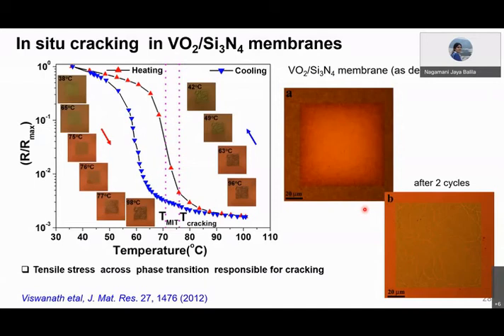Yeah, in this case, if you look very closely, the cracking happens only in the freestanding square membrane. The silicon nitride is coated on a silicon substrate. The outer region is thick, whereas the interior square region is a membrane. In my opinion, whatever stress the VO2 is imposing, the membrane is not structurally stable enough to withstand. So it is not cracking in other places, only the membrane is getting cracked.